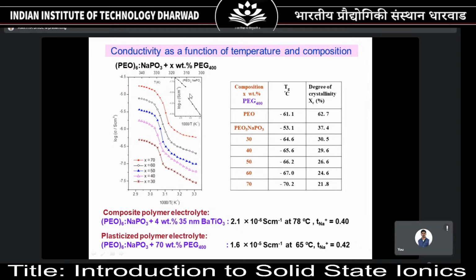Look at the graph that I have shown you before that. There were 2 different regions for conductivity in the case of the host polymer, that is polyethylene oxide and sodium metaphosphate: the region below softening and above softening. Now that softening is not visible, but it's a smooth transition. It happens smoothly and continuously, and conductivity has enhanced. As we increase the content of polyethylene glycol, the conductivity also enhanced.